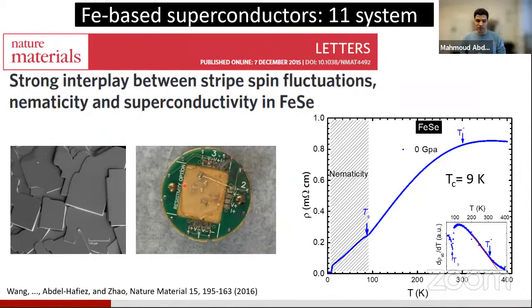And what you see here is what we call the puck for transport measurement, that can be implemented in a physical property measurement system. And as you can see, 1, 2, 3, you can put 3 samples and measure 3 samples in one stage. You cannot see it, but you should believe me, there is a sample here, because it's really in microns. So we do that in a glove box and also under an optical microscope.